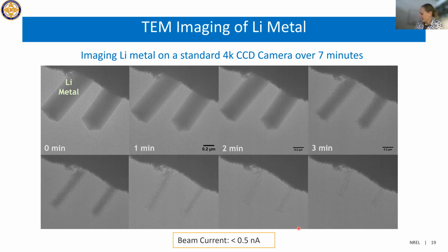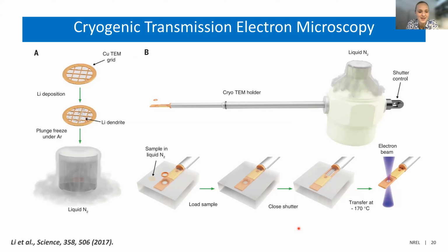And so in 2017, I was very excited to see this paper come out by Yi Cui's group at Stanford, where they showed that you could electroplate lithium onto a copper grid and then plunge it in liquid nitrogen, load it into a Cryo-TEM holder, which is just a liquid nitrogen dewar that has a metal rod going down the tip of the holder to keep it cooled during imaging in the microscope. And so they use this to then image lithium metal after cycling and look at SEI character.